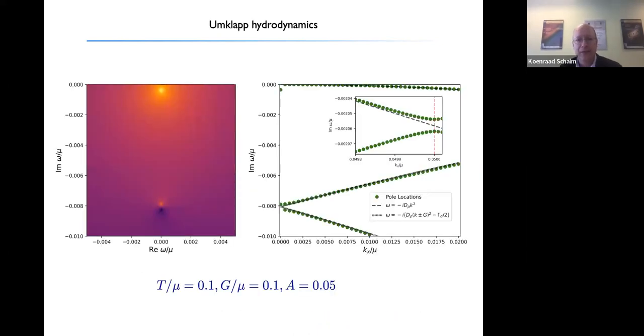And here's an example. This is now the sound mode, where you see this level repulsion in the hydrodynamic modes at the edge of the Brillouin zone, precisely at half lattice vector.